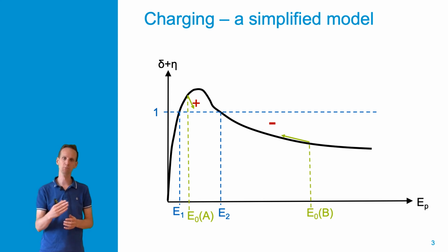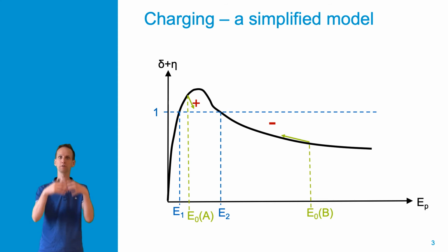So we gradually move up the curve, and we would reach an equilibrium stationary situation when the yield would again approach a factor of 1. However, we should also realize that the charge buildup may be so high that the total electron beam may be reflected and that the signal we detect actually originates from the objects inside the electron microscope.